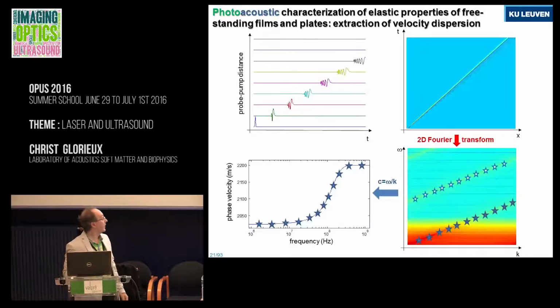You can also see it in this kind of graph, an x-t matrix. This is the signal displacement, which can be positive or negative, as a function of space and time. The wave package has some kind of speed, but it's broadening because there are components that travel a bit slower, as you can see here. So it's dispersive. On the bottom left you see the theoretical dispersion curve. How can you determine it experimentally?